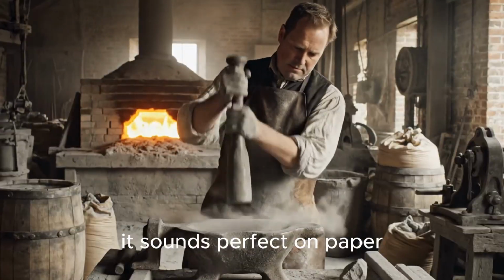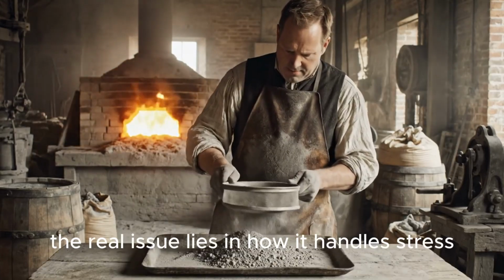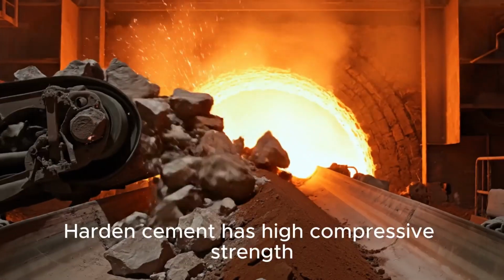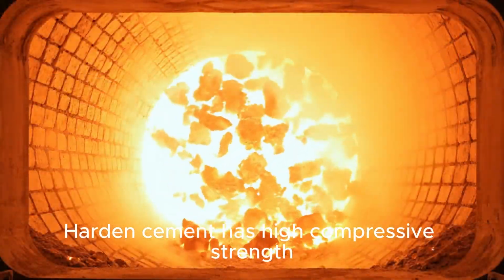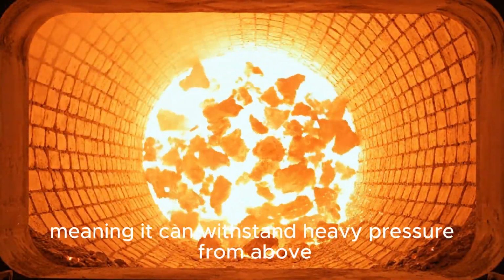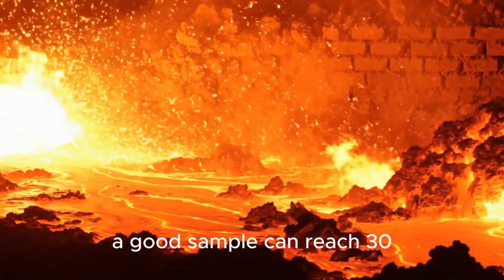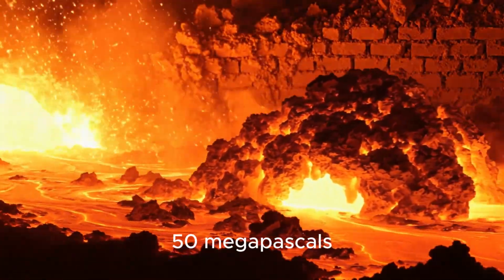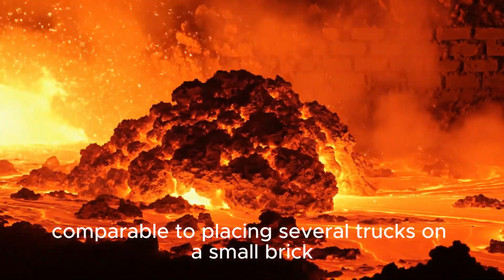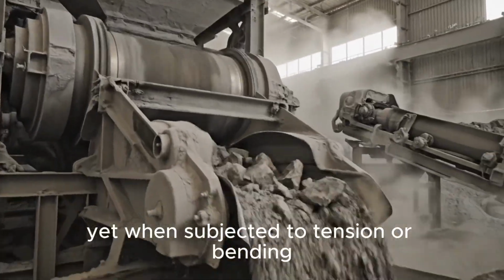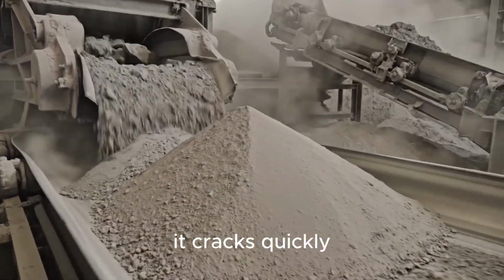It sounds perfect on paper. The real issue lies in how it handles stress. Hardened cement has high compressive strength, meaning it can withstand heavy pressure from above. A good sample can reach 30-50 megapascals, comparable to placing several trucks on a small brick. Yet when subjected to tension or bending, it cracks quickly.